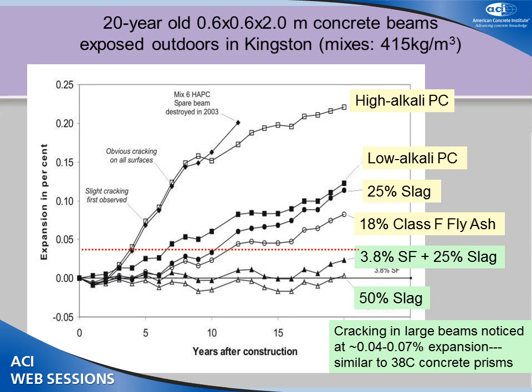So let's look at the beams. These are the unreinforced beams, and we see expansions up in the neighborhood of about 0.2, as high as 0.23. If I go back, we were measuring about 0.16, 0.17 in the concrete prism test in the laboratory at 38 degrees, but we're even getting higher expansions in the field in that same time, well, a slightly lower time frame, but in about the same time frame, we're seeing similar expansions to what the concrete prisms at 38 showed.